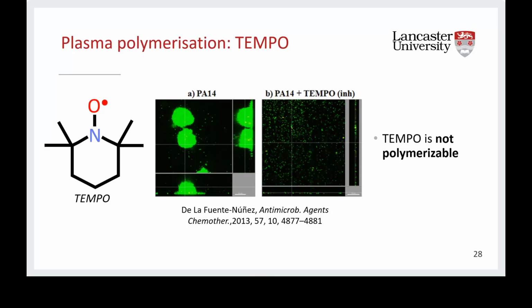Actually, TEMPO has anti-biofouling activities. You can see in figure 1a the bacteria, which are the green spots, on a surface, which is the black part, and the same bacteria after being exposed to a solution of TEMPO in water. Now, the bacteria have left the surface. So TEMPO is an extremely interesting molecule, but we cannot coat the surface with it because it has no carbon double bond, so it cannot undergo radical polymerization.